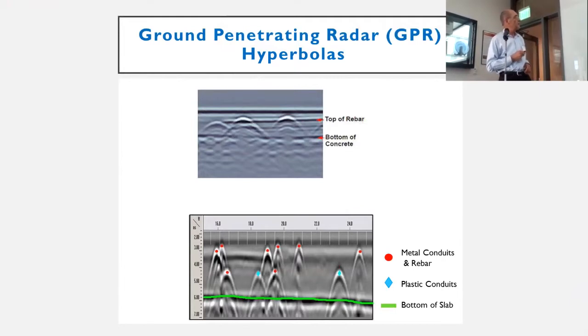We have a typical basic GPR survey result. And this, again, as I said, will come out on this small screen here. That'll show us these hyperbolas. So it's very easy to use once you get to know how to do it. Now, as we become more sophisticated with this, we can go down to the lower chart. And this shows that not only can we pick up rebar or PT cables, it can also pick up conduit. And it also picks up plastic or metal, and also shows us the bottom of the slab, which is very important. So we don't even need to measure the thickness of a slab or a wall.